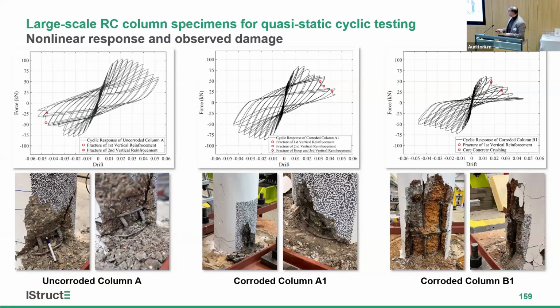And this is the global response. This is the uncorroded, well-confined column designed according to Eurocode 8, but you will see you still get some buckling under the cyclic load, and you see this fracture. This fracture is known as low cycle fatigue behavior. In a normal structure we have low amplitude loading and high cycle fatigue, with millions of cycles. In an earthquake, it is high amplitude, low cycle fatigue. That means the amplitude of the loading is high, and with just a few cycles we get fracture because of the plasticity. And when we get buckling, we get a double effect.